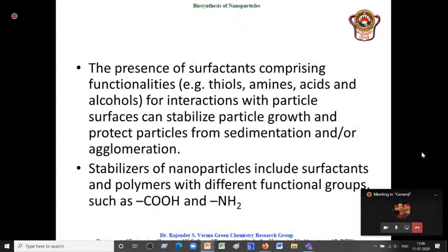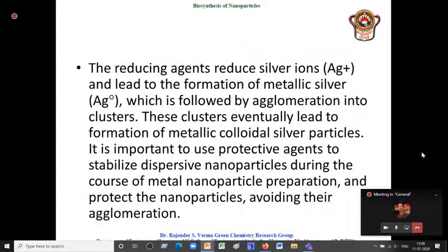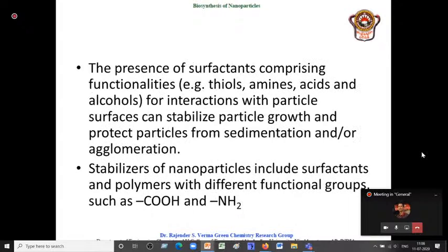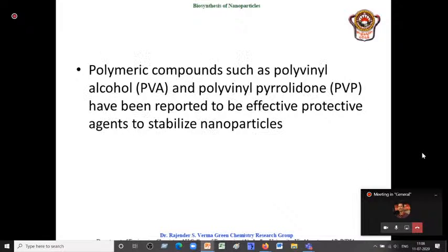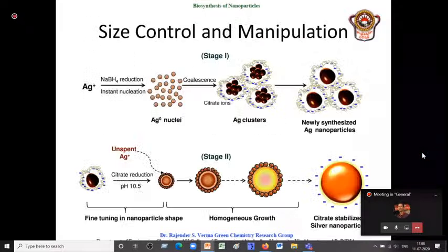Once I have it, I should know what reaction is to take place. The second thing I should know is that it should not be agglomerated, and it should be in its nano size only. For that, I just want to show you this. This is what happens in many formations of nanoparticles. If you take silver salt, it will contain silver ions. If you use a chemical reducing agent like sodium borohydride, in a fraction of a second silver nanoparticles will form with Ag0 as the nuclei form, and slowly they will form silver clusters.